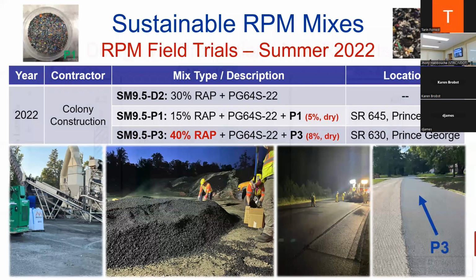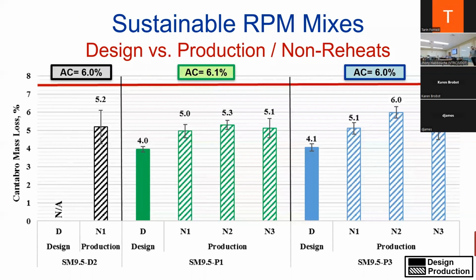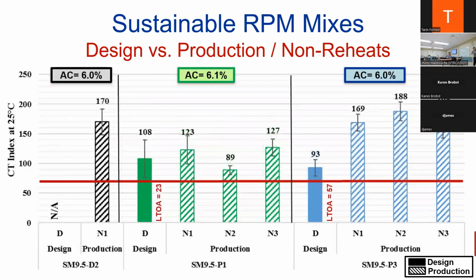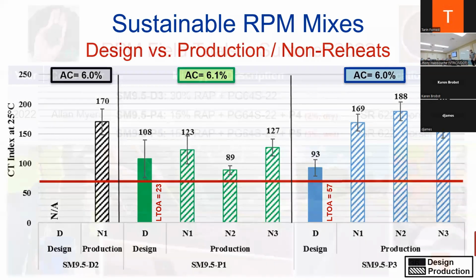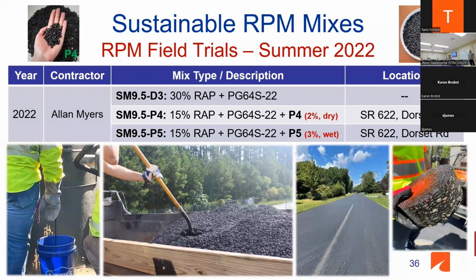Looking at some of the performance data, you'll see that durability-wise, we had similar or better. I don't want to go into the numbers, I'm just giving an overview. And cracking performance and tolerance performance were way above the 70 that we're looking for. You'll see that your plastics are way better compared to the control, similar or better, as well as rutting, which will never be an issue because that stiffens the material. And then we had another trial off of Route 60, if I'm not mistaken, on Dorset Road, where we used another type of plastic, P4, and another plastic, P5. That's the mix being produced, and then we placed them.